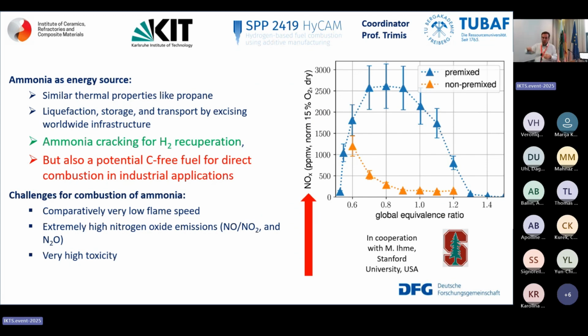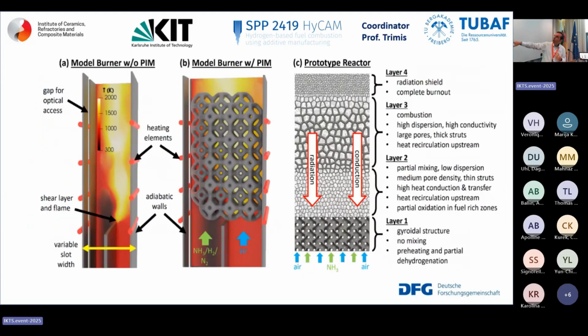Why? Because if you put air and directly NH3 to fire H2, you will get a much higher amount of NOx. And you don't want to say CO2 out, but NOx high. So you have to get a compromise of the processing issue. And it's not only a gyroidal structure, it's several pore structures that have to be combined, have to be engineered by young guys like you in order to meet the demands of the combustion. And you have to do it not only fine-grained, you have to do it also coarse-grained. Because you don't need only small issues, you need also big issues.